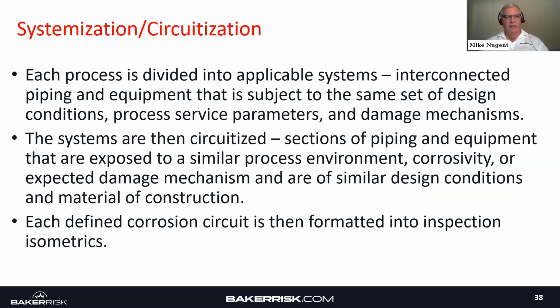The system and circuitization is the key to not overdoing it, and to properly capture the damage mechanisms in a specific circuit or a system. What I've tried to do in my implementations, which I've done probably over 75 different risk-based implementations and or updating, or what we call evergreening, is divide it into the appropriate systems, interconnecting piping that's subject to the same set of conditions, process service parameters, and then we circuitize these.